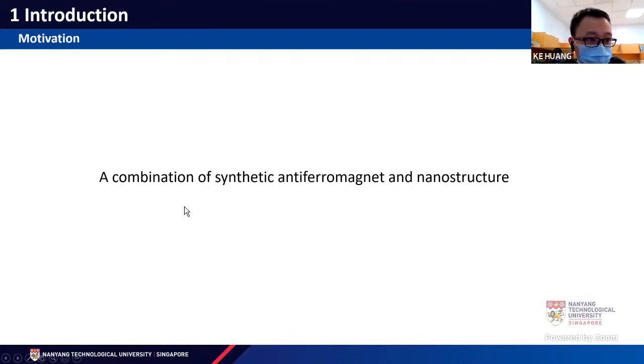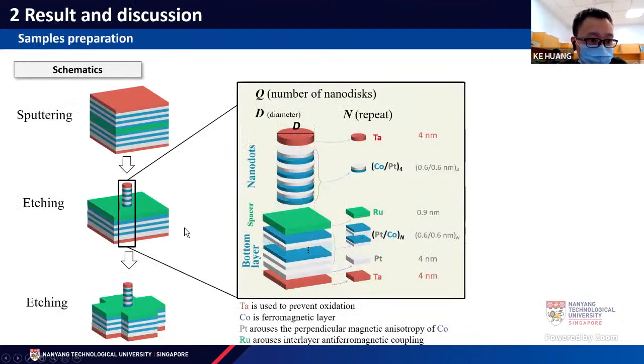So my research asks: what if we combine the nanostructure and the synthetic antiferromagnet? What can we get? Here is our sample. We use sputtering to deposit multiple layers, and then we etched all the layers above the ruthenium into a circular nanodisk. The top and bottom tantalum is used to prevent oxidation. Then we have the top cobalt-Pt and bottom Pt-cobalt, which are ferromagnetic. It's a perpendicular ferromagnet, and this is our sample structure.